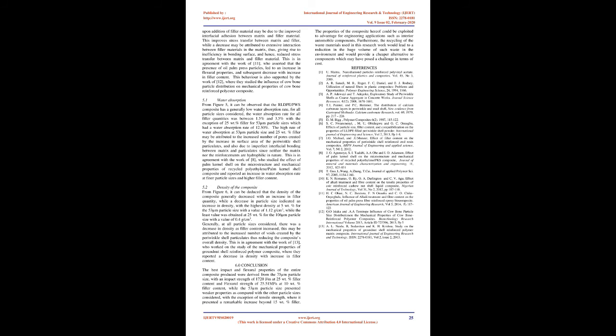The control sample had a flexural strength of 14.79 MPa, which shows that the increase in filler produced an increase in flexural strength but decreased as the filler content increased to a point where there was extensive interaction between particles of filler material. The increase in flexural strength upon addition of filler material may be due to the improved interfacial adhesion between matrix and filler material. This improves stress transfer between matrix and filler, while a decrease may be attributed to extensive interaction between filler materials in the matrix, thus, giving rise to inefficiency in bonding surface, and hence, reduced stress transfer between matrix and filler